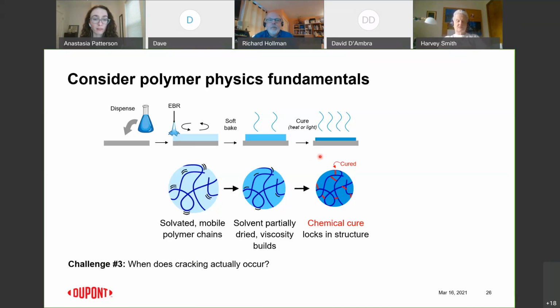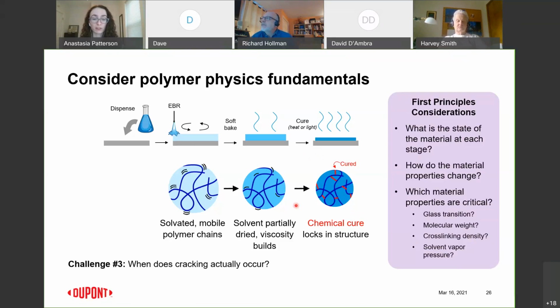We wanted to consider all these different physical properties and states of the material at each of these stages. And we learned that the cracking actually starts at the soft bake step, so not where we expected. And it really highlighted that need for us as material designers to be in touch with the actual process, so we can make the right changes to fix the problems.